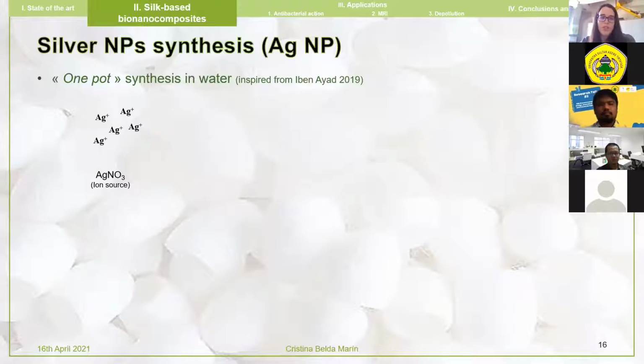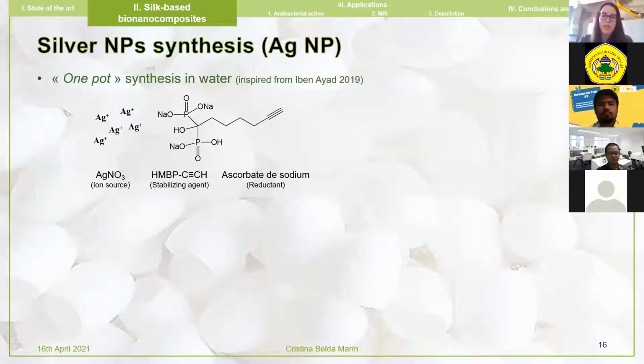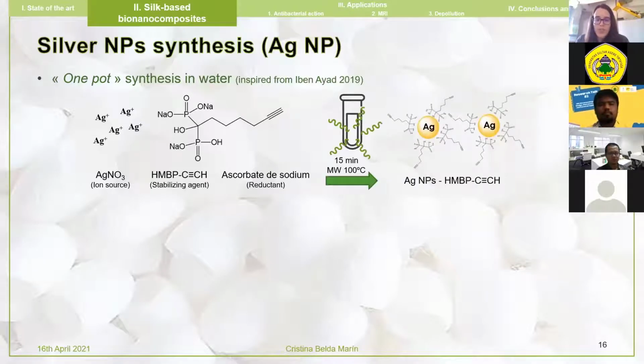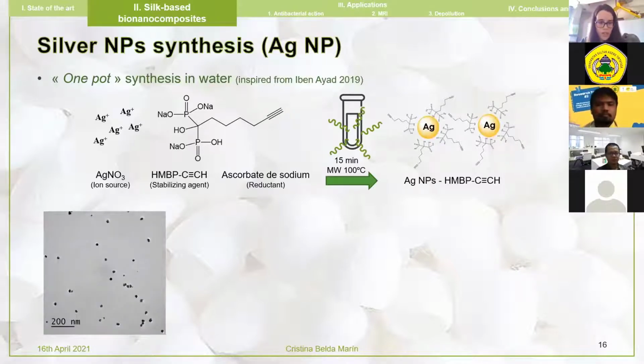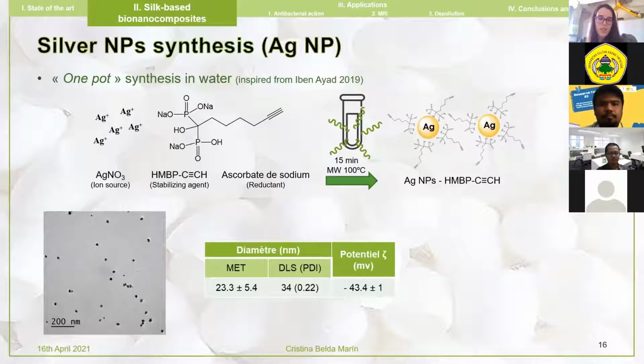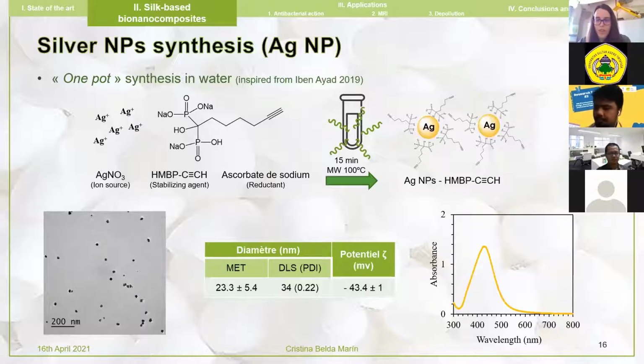Slightly the same procedure was used to synthesize silver nanoparticles, in which we have silver nitrate as an ion source. We add our stabilizing agent and reductant, and this time we need to heat the suspension with microwave during 15 minutes to get our silver nanoparticles. So again, we have spherical nanoparticles that are monodispersed in their synthesis. This time they are a little bit larger and without aggregation seen in the dispersion. And again, the light absorption properties are well in accordance with what's seen in the literature for silver nanoparticles.